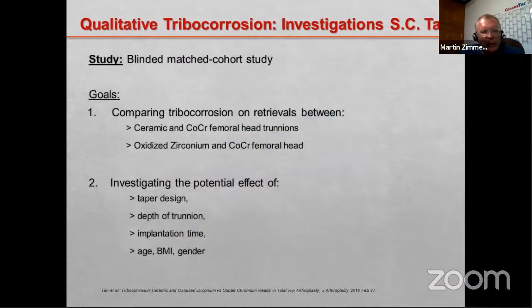There is actually another study by the group of Tan, which also analyzed retrievals. There were two groups in this study: first, ceramic versus cobalt chrome, and oxidized zirconium versus cobalt chrome. The intent of this study was to study the effect of taper design, specifically the size of the taper, the depth of the trunnion, and the implantation time on the fretting corrosion issue.